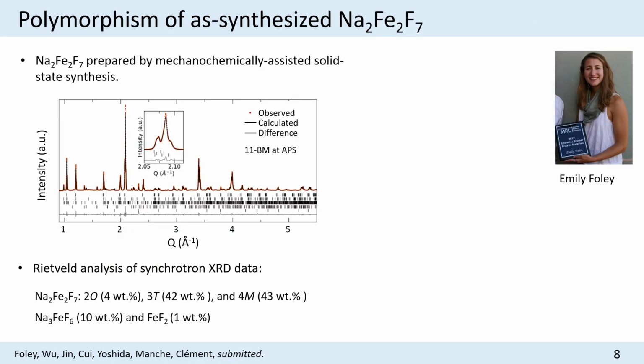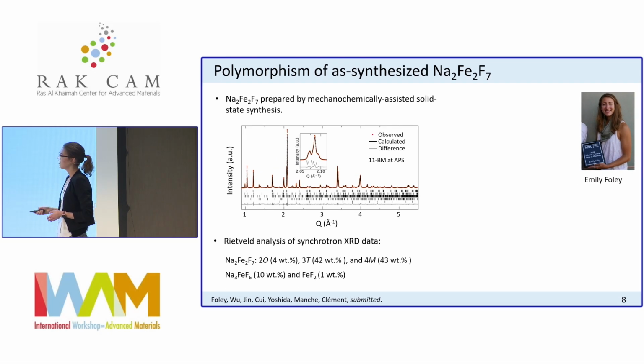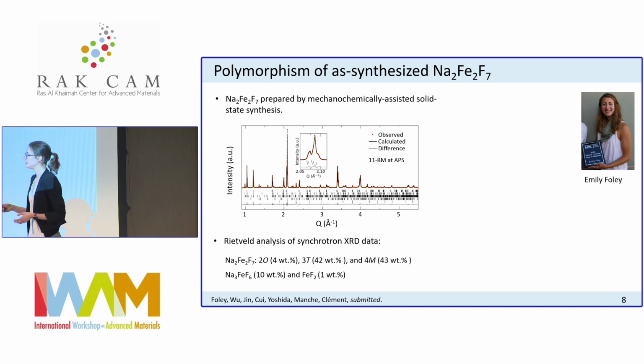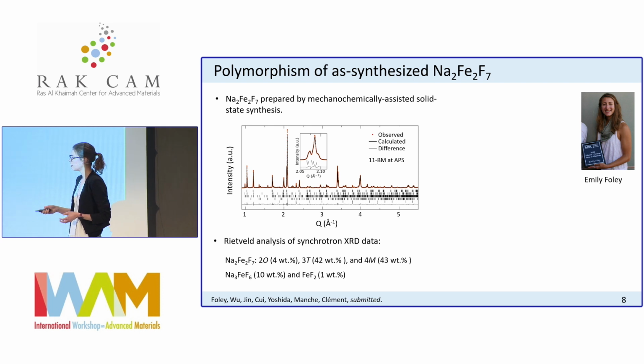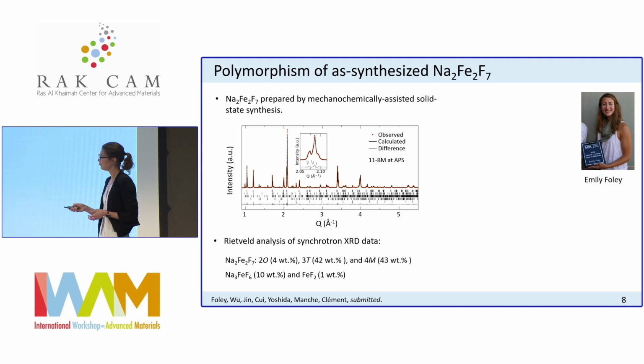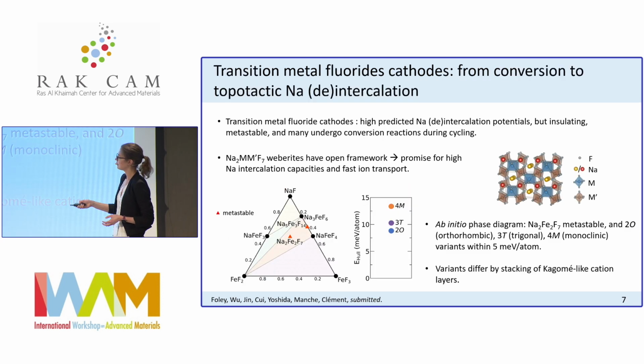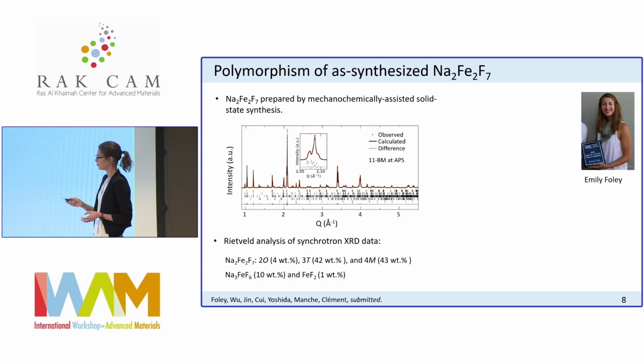This is work led by my student, Emily Foley. When she did these first principles calculations, she continued by synthesizing the material. This is a material synthesized by solid state synthesis and mechanochemically assisted. And this is the synchrotron XRD pattern that you get on the product. If you do a Rietveld refinement of this pattern, you find that the Weberite structure is the dominant phase in the sample, but it is multiphasic, so you have 3 different polymorphs of this Na2Fe2F7 Weberite: an orthorhombic polymorph, this 2O polymorph, a trigonal polymorph, the 3T, and then a monoclinic polymorph. And then you have some impurity phases. Unsurprisingly, these are the impurity phases that are on the hull, so the ones that are thermodynamically stable.